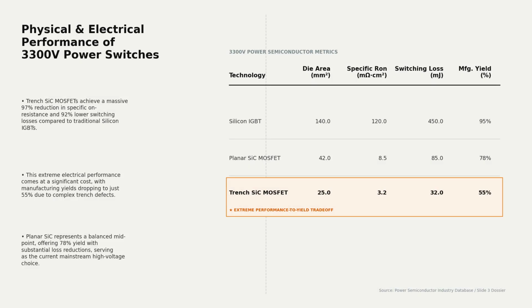The transition to trench silicon carbide architectures represents a major electrical performance leap offset by manufacturing complexity. Trench devices achieve a specific on-resistance of 3.2 milliohms square centimeter. This is a 62% reduction compared to planar silicon carbide and a 97% reduction compared to legacy silicon. This architecture enables a highly compact die size of 25 square millimeters. This physical compaction theoretically increases the gross number of dies per wafer by 68% over planar designs.